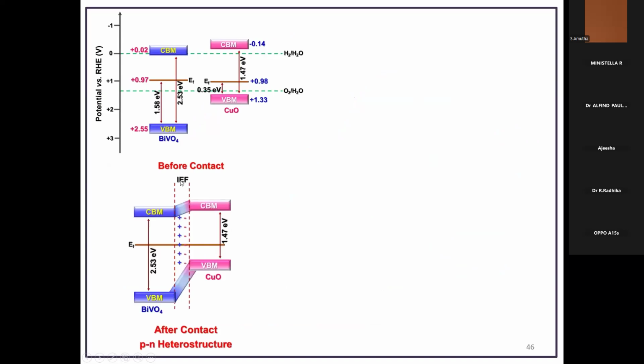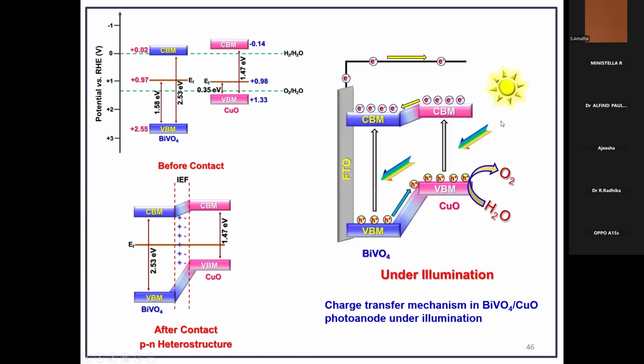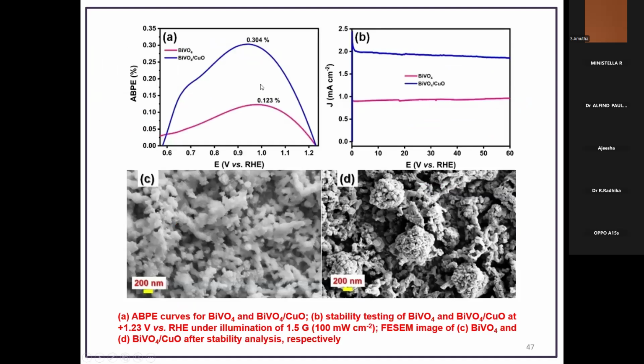So it creates an internal electric field at this space charge region. Then it is subjected to illumination with water. It will oxidize the water into oxygen and protons. That proton will accept the electron in the cathode chamber. Then finally it will produce hydrogen. So this is water. The stability also we have checked. It shows good material stability. The durability also, it is able to constantly produce hydrogen. Then the efficiency we have calculated. It is almost closer to the benchmark value, 0.3 percent.